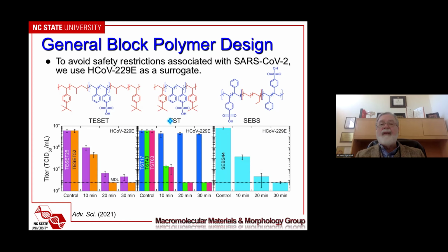But we can also go to a more generic polymer. This one is available from many different distributors, and it's relatively inexpensive. And so we can, in fact, sulfonate the end blocks of this material, noting that if we sulfonate too much, then this polymer will dissolve in water. But if we keep it at 44 mole percent, we actually have a stable surface, and it also works quite nicely.